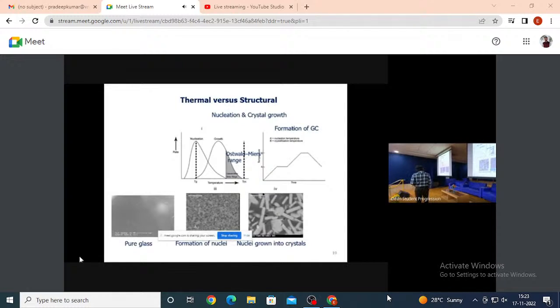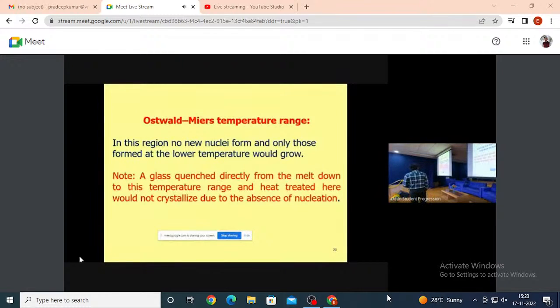Here you can see for this first nucleation process, we heat the sample with a certain heating rate, 5 degrees centigrade per minute or 10 degrees centigrade per minute, and we stay there for 4 hours or 10 hours. Again, we heat the sample with a different rate and stay there for some time. Then only we get this. Otherwise, if we don't follow this sequence, we get something different. There is one particular temperature region where we don't get the crystal growth. That is known as the Ostwald–Miers temperature range.